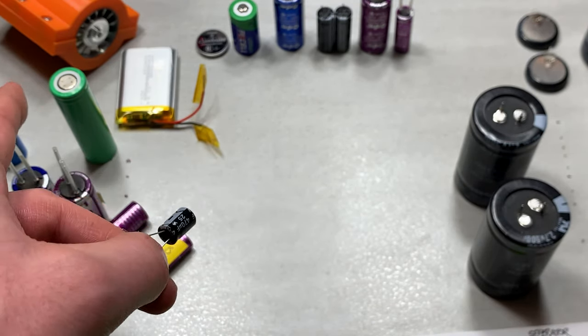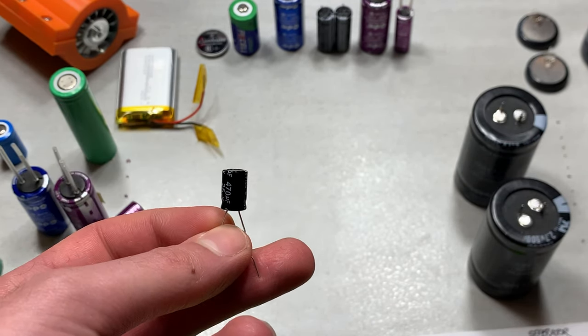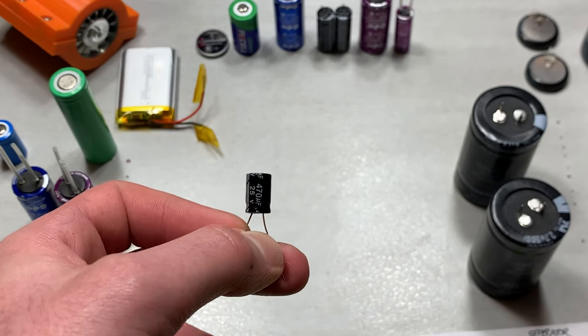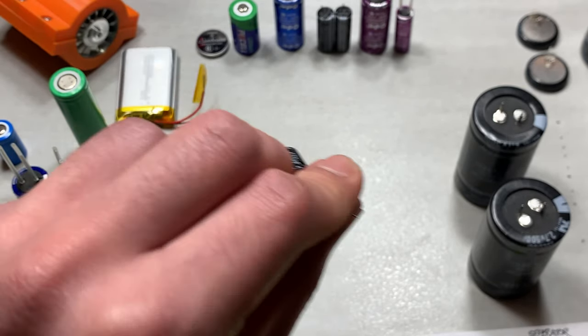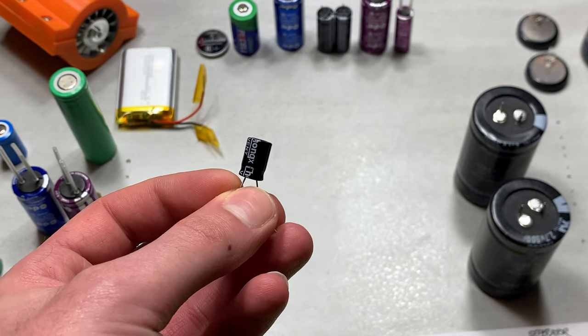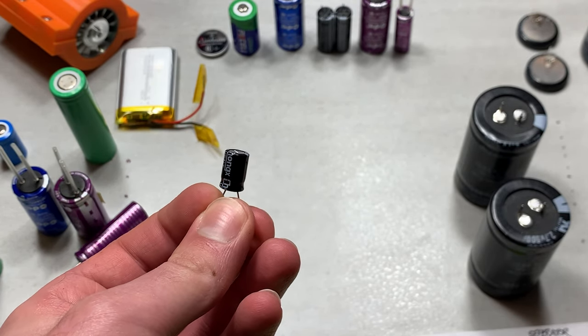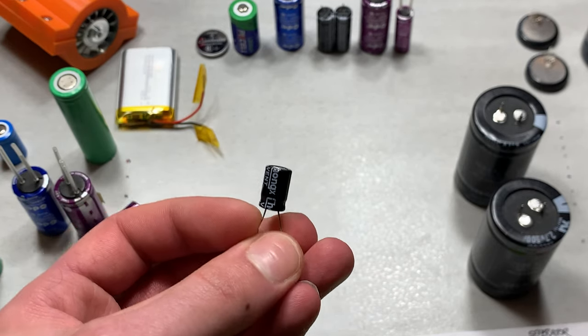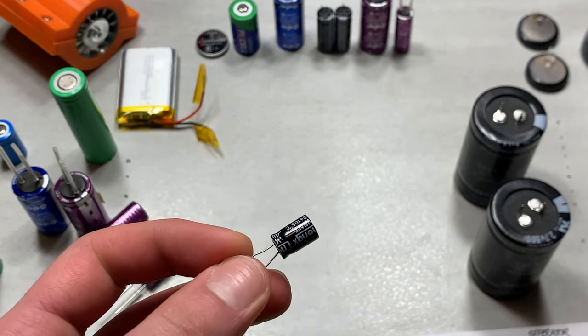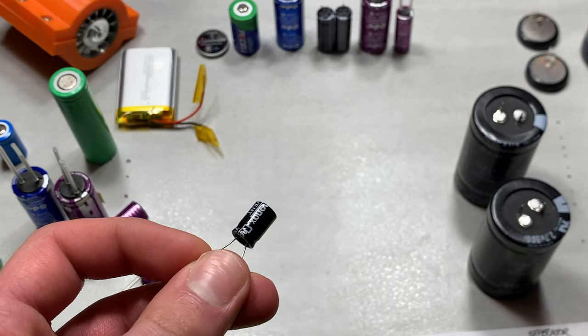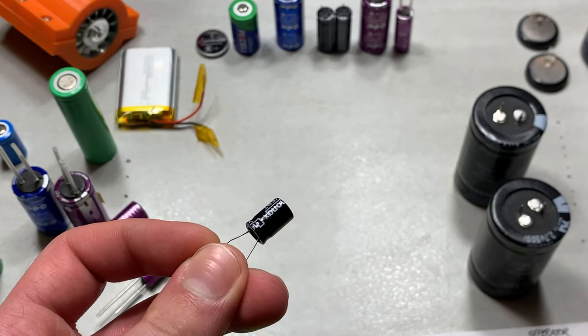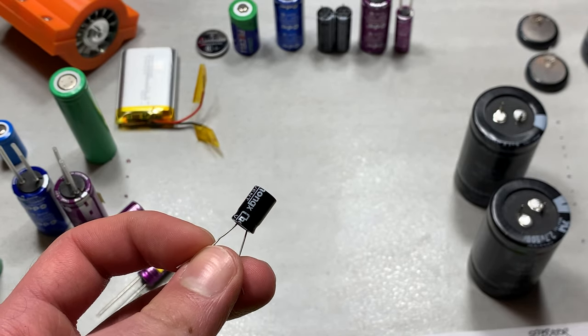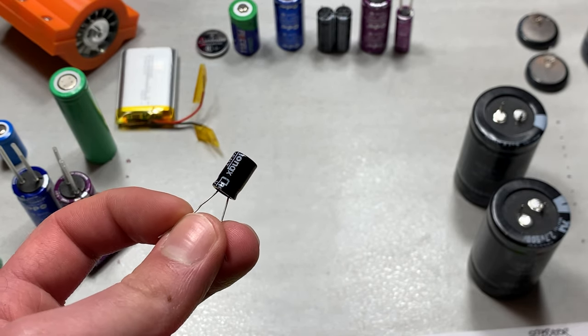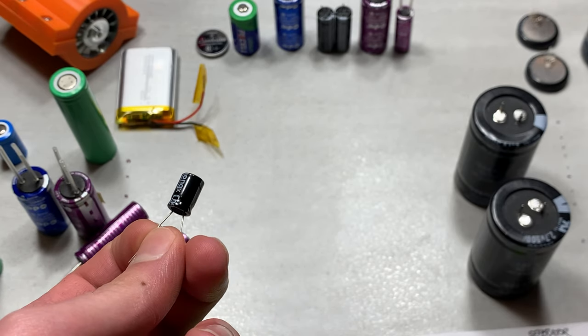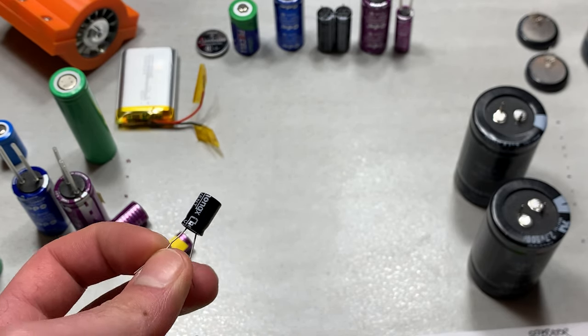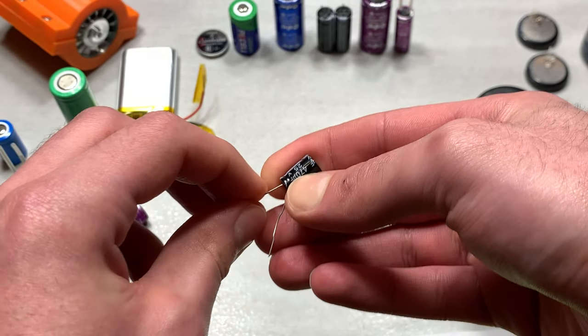And while I believe that the 18650 batteries are manufactured in a similar fashion, as far as I can tell, the layers that they apply the materials on are much thinner on the capacitors than in the batteries. And if that is the case, then that would mean that you have a much lower current density over your two electrodes, which, connecting that to what we just read on the website, Battery Power Online, where they conducted a study for dendrite growth versus current density, it would be quite easy to, well, not quite easy, but it could potentially,